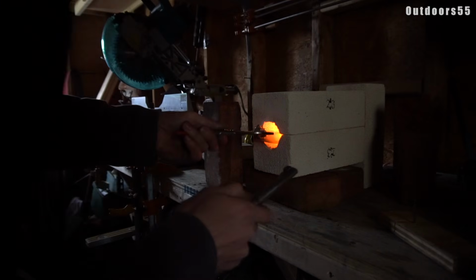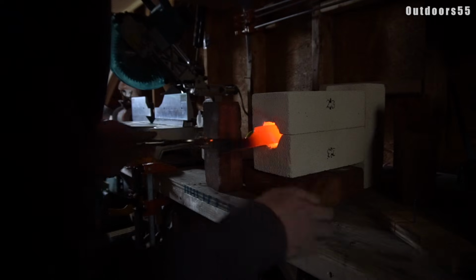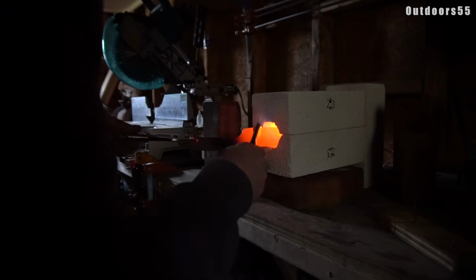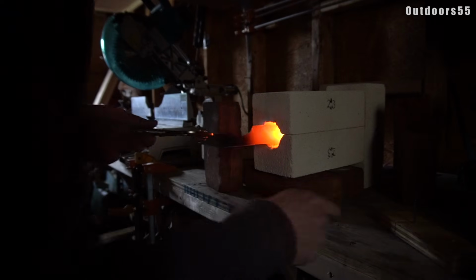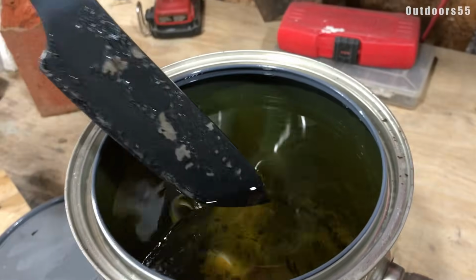Typically what I do is turn the lights off in my shop so I can see the color of the steel. I'll also use a magnet to test the temperature of the steel as it becomes non-magnetic at around 1425 degrees Fahrenheit. Once the steel becomes non-magnetic, I put it back into the heat for a minute or so just to get that little bit of extra heat into the blade. Then I quench in canola oil that's been heated to around 130 degrees Fahrenheit.